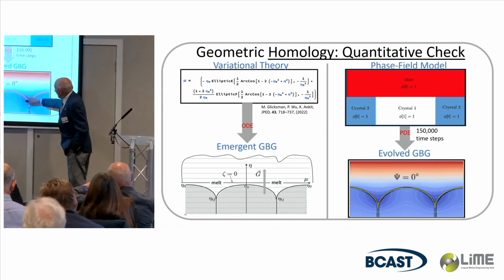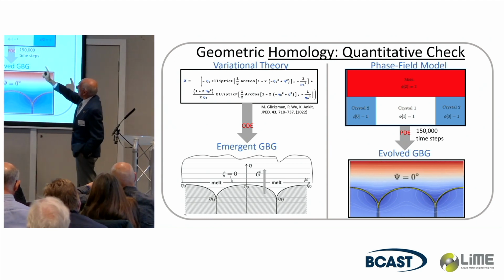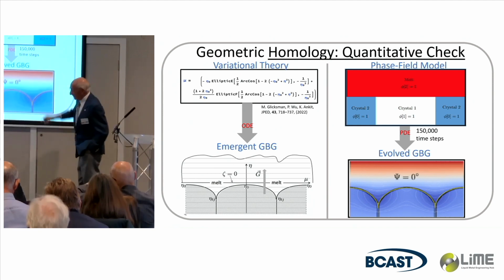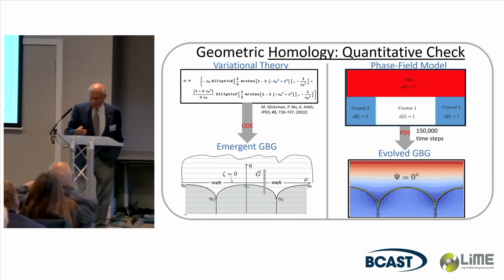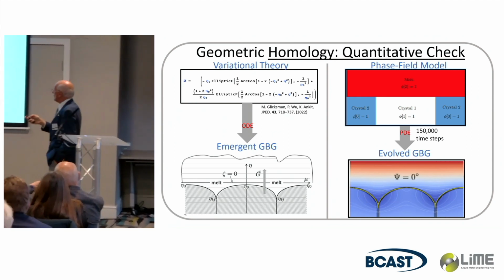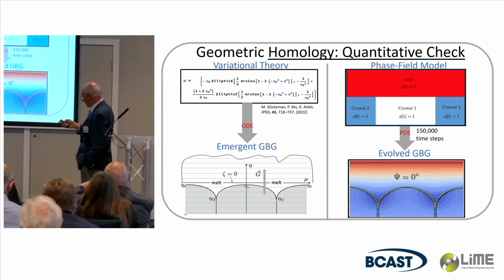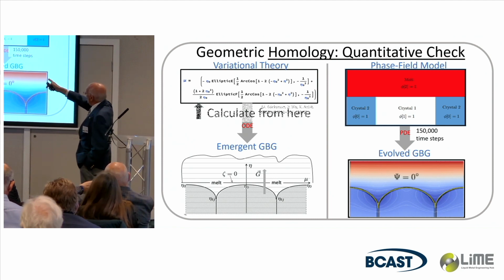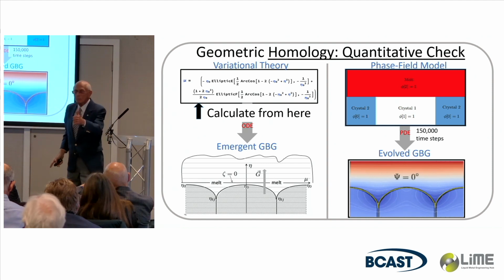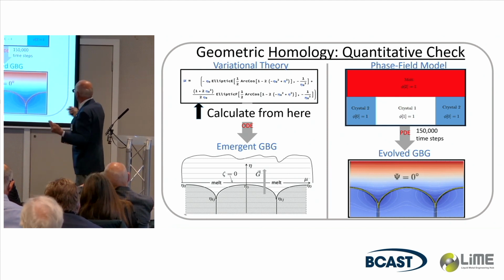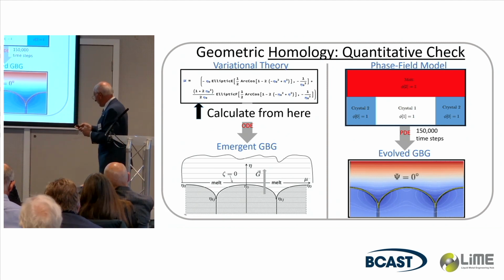This yellow curve shows the comparison of adjusting the parameters to fit the evolved shape. Here's the difference, though, and this is the critical point of the whole exercise. You calculate from field theory everything exactly: the chemical potential, the gradients of the chemical potential, the fluxes that are traveling through the interface under those gradients, which result in either heating or cooling, as I'll show you.